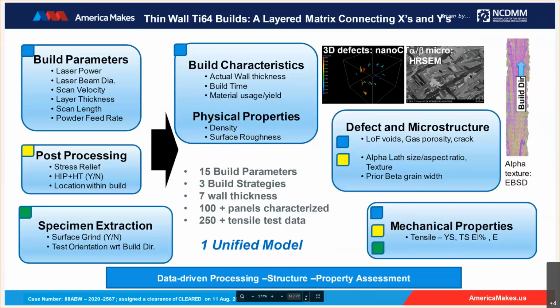So if you have the build parameters, for example, power, feed, speeds, scan lengths, and beam diameters, all of this is connected to the build characteristics, which is the actual wall thickness that you build and the time and the yield that it took to build those walls, along with the physical properties that were measured in terms of quantities like densities and surface roughnesses. Now, if you take it one level deeper, if you look at post-processing, which is you extract the walls from the builds, and you basically subject it to stress relieving or HIP and heat treatment.